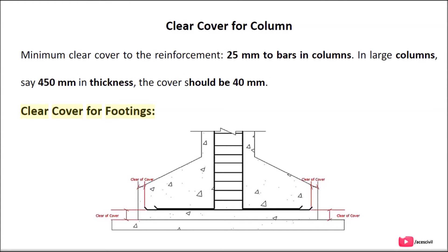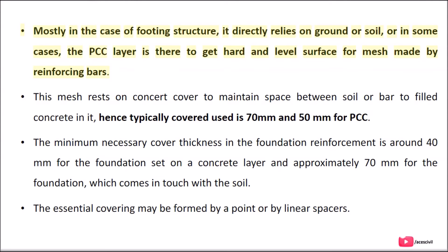Minimum clear cover for footings: In the case of footing structures, it directly rests on ground or soil, or in some cases a PCC layer is used to get a hard and level surface for the reinforcing bar mesh. This mesh rests on concrete cover to maintain space between soil and bar. Typically, 70 mm cover is used when in contact with soil and 50 mm for PCC. The minimum cover thickness in foundation reinforcement is around 40 mm for the foundation set on a concrete layer and approximately 70 mm for the foundation in contact with soil. The essential covering may be formed by point or linear spacers.